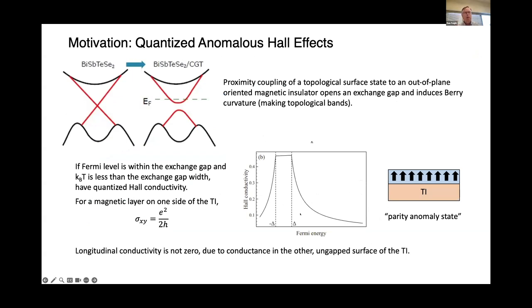So just some background about what happens when you combine a magnet with a topological insulator. If you have a magnet with out-of-plane magnetization, that can produce an exchange gap in the topological surface state. And if you can position the Fermi level within that exchange gap, the Berry curvature from that exchange gap gives you a large Hall effect. And it's an anomalous Hall effect.